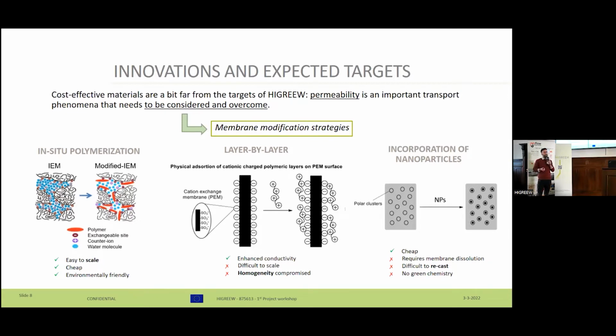In this process, we need to dissolve our commercial membrane and then make a colloidal suspension with such nanoparticles and then recast. This is an interesting procedure because it's also cheap, but it requires membrane dissolution, and the chemicals involved in this procedure are not considered so green chemistry. And the critical step in this procedure is then the recast.